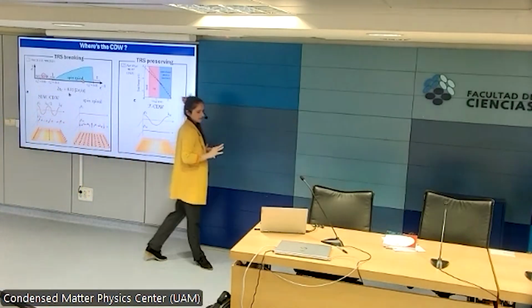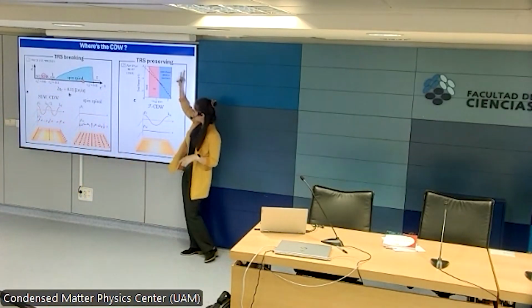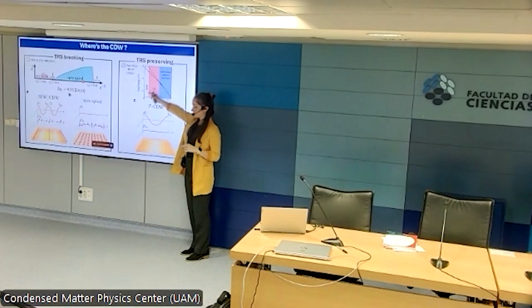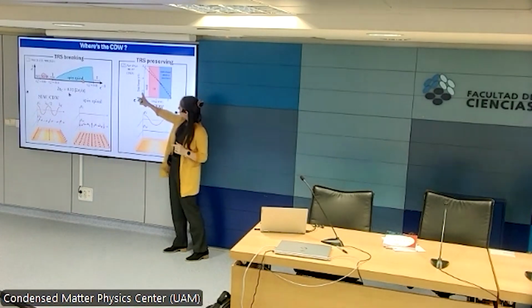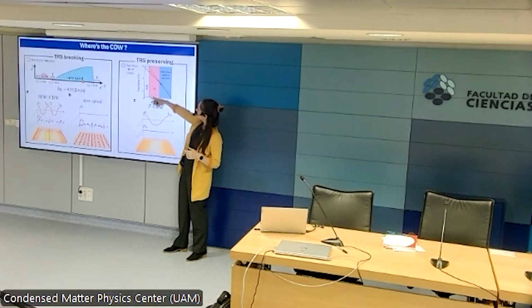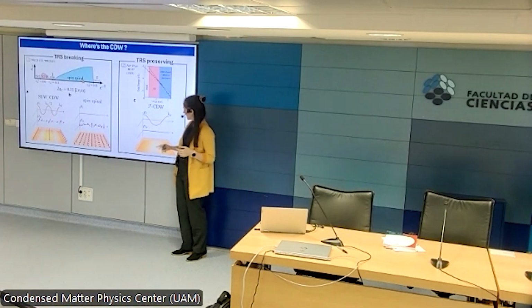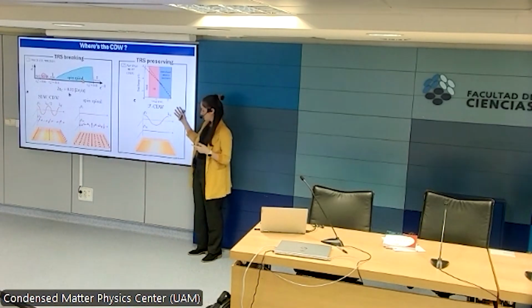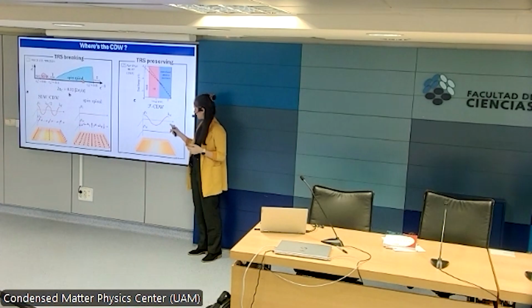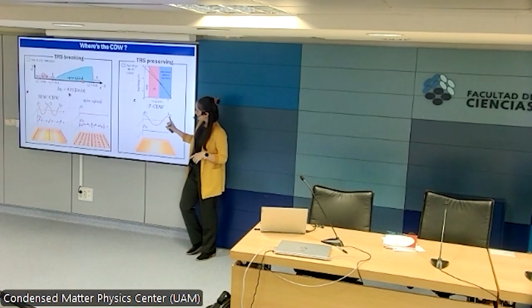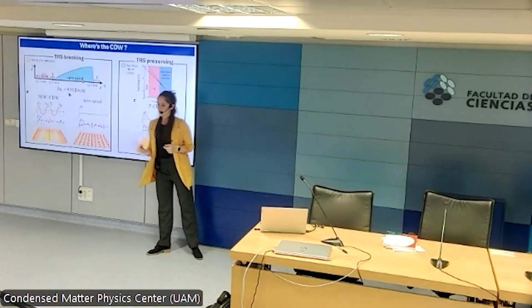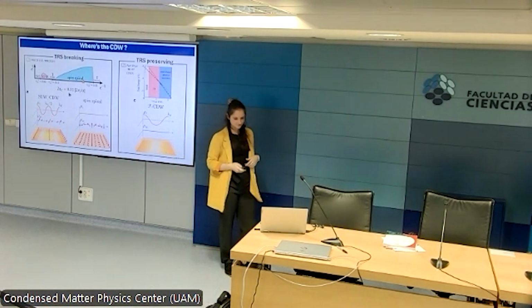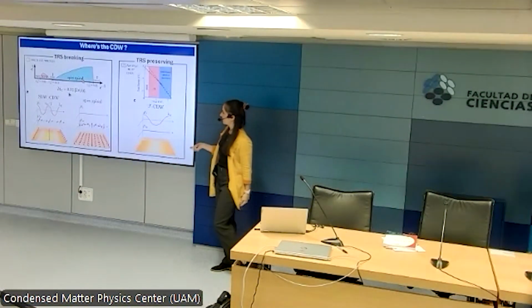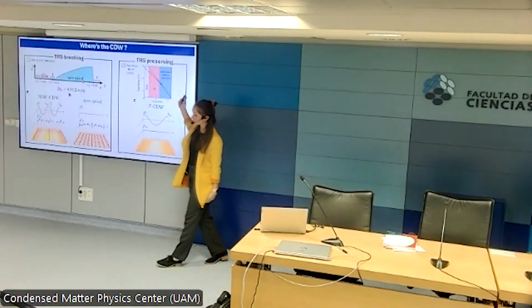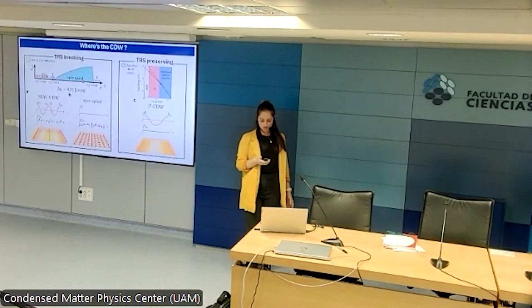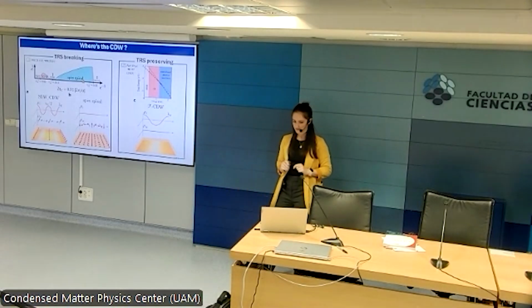In case the ground state is actually in a time reversal symmetry preserving state, the excitonic insulator state predicted is only one. It's bordered by a metallic phase on one end and then a correlated atomic insulator on the other. And it has a charge density wave associated to it, no spin density wave. And notice that the periodicity of this is double the periodicity of that. So what we wanted to do is try and figure out whether we were in the time reversal symmetry breaking or preserving state, and which order parameter was characterizing our system.